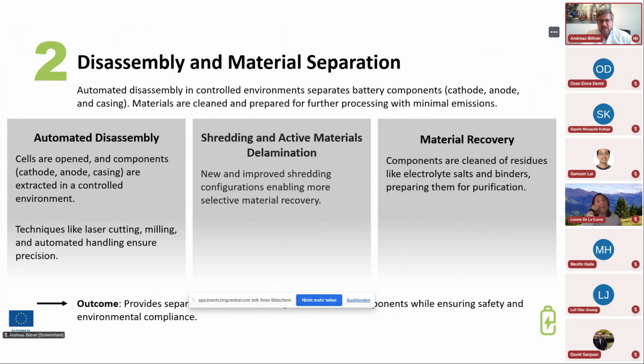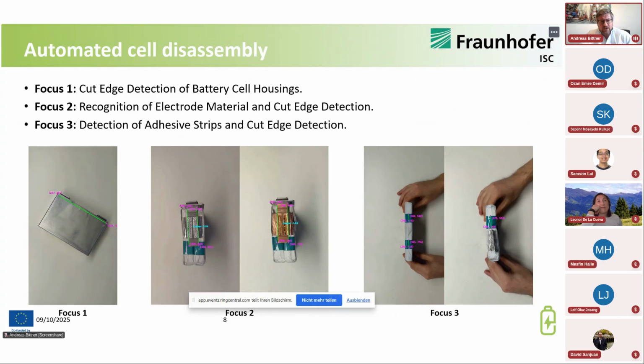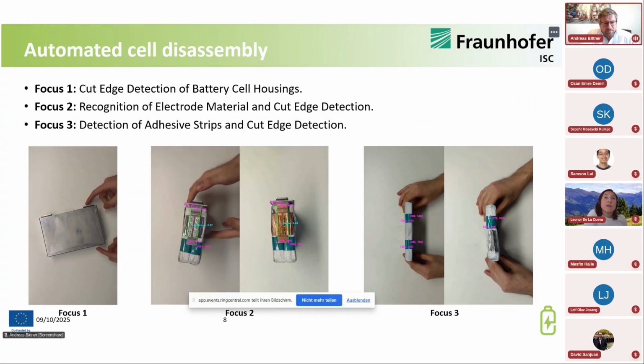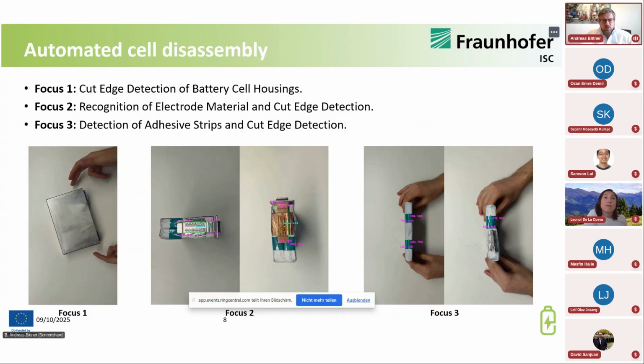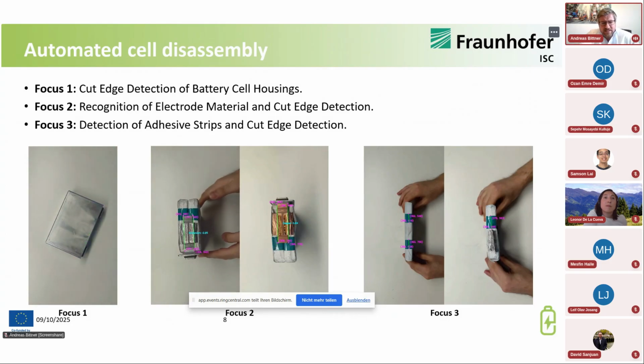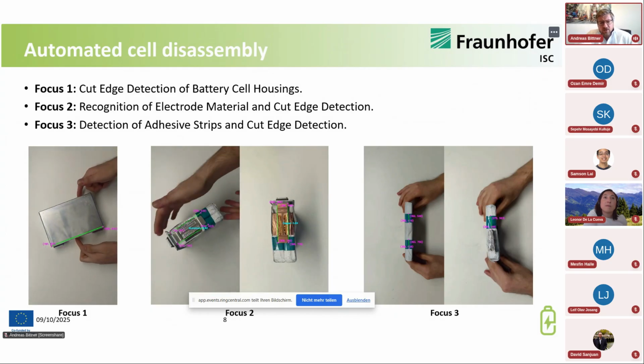A nice example by Fraunhofer. The first step in our automated cell disassembly process is the opening of the battery cells and the extraction of the electrode wraps. And you can see in focus 1, the cutting line in green that is automatically adjusted when the cell is moved. Focus 2 shows the second step, the extraction of the electrode wrap out of the compound. And therefore we have to cut the connection between the copper and aluminum current collectors and the respective aluminum and copper pads. Also here you see the green cutting line. And focus 3 then shows the last step, the cutting of these small glue stripes to be able to unfold electrode wraps in subsequent steps that are also automated.